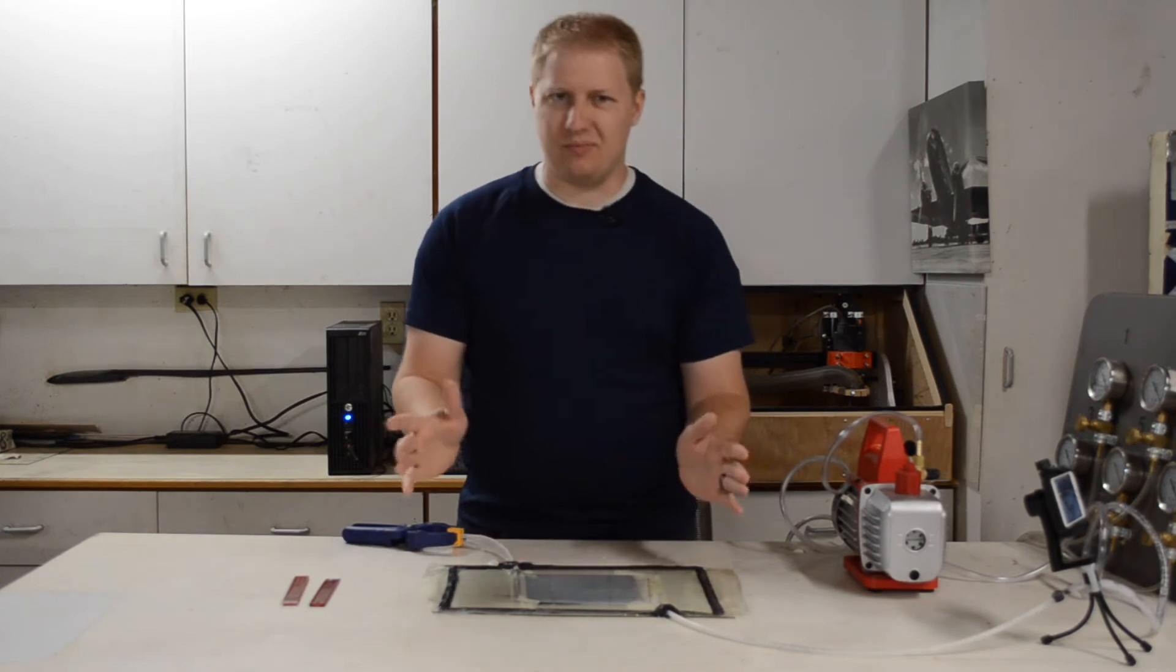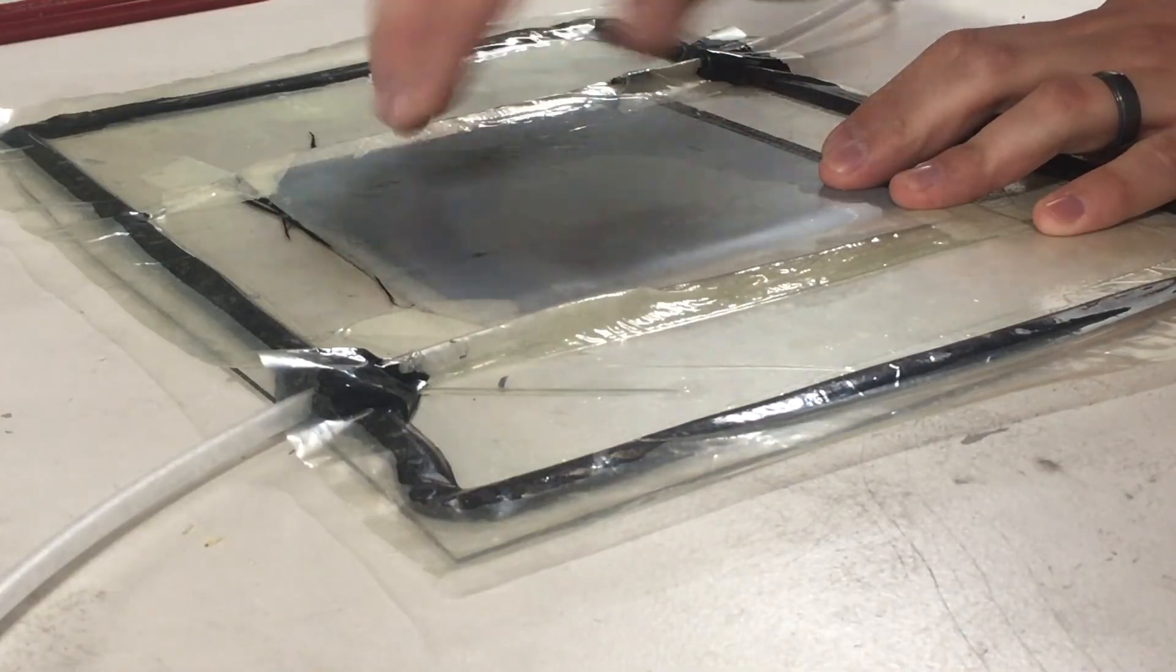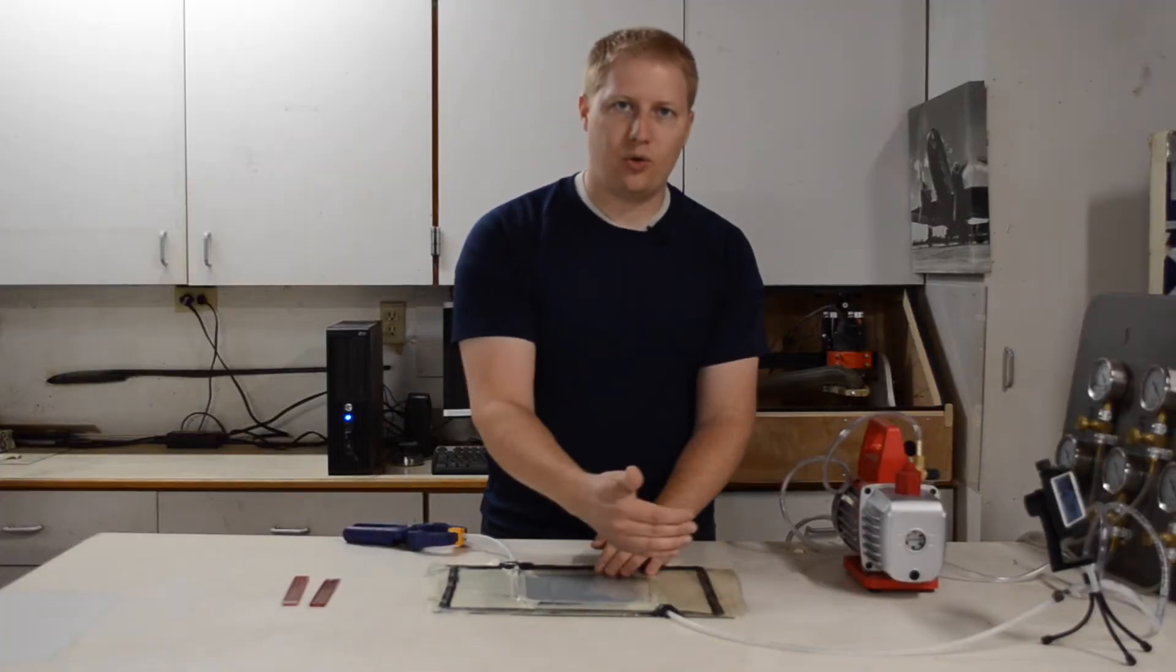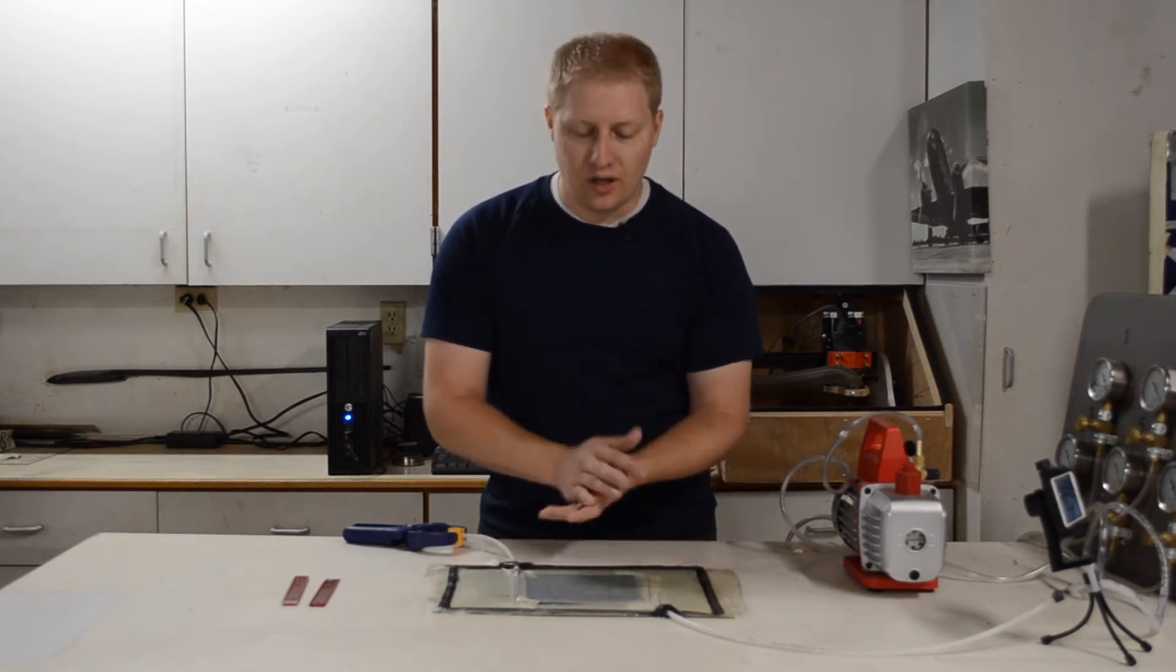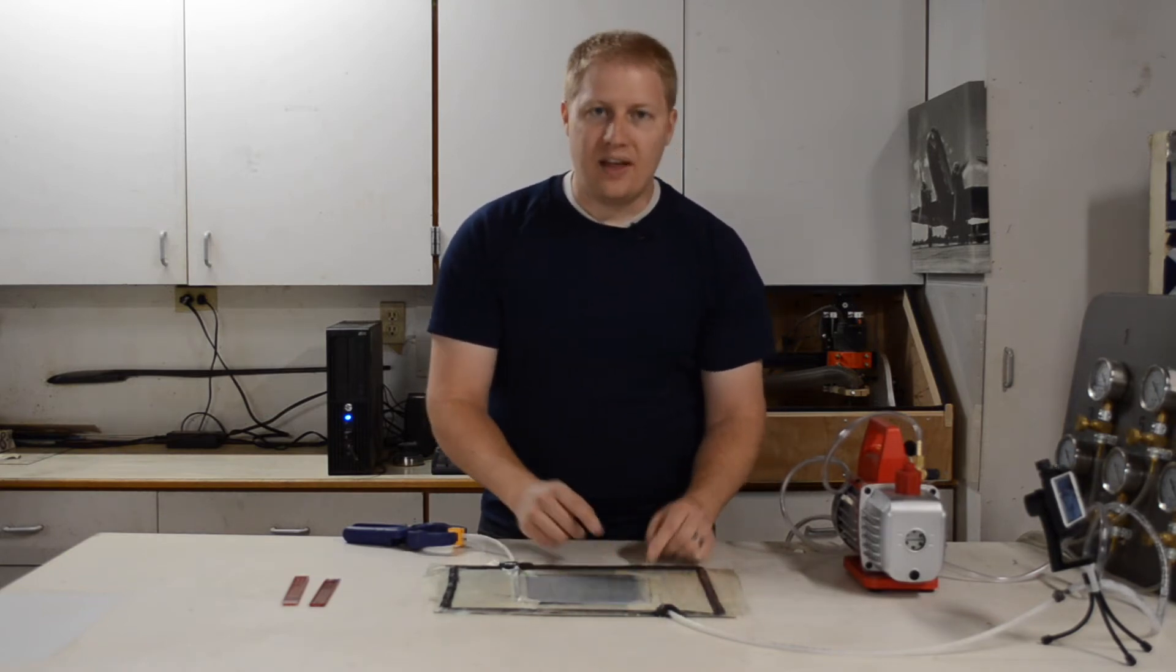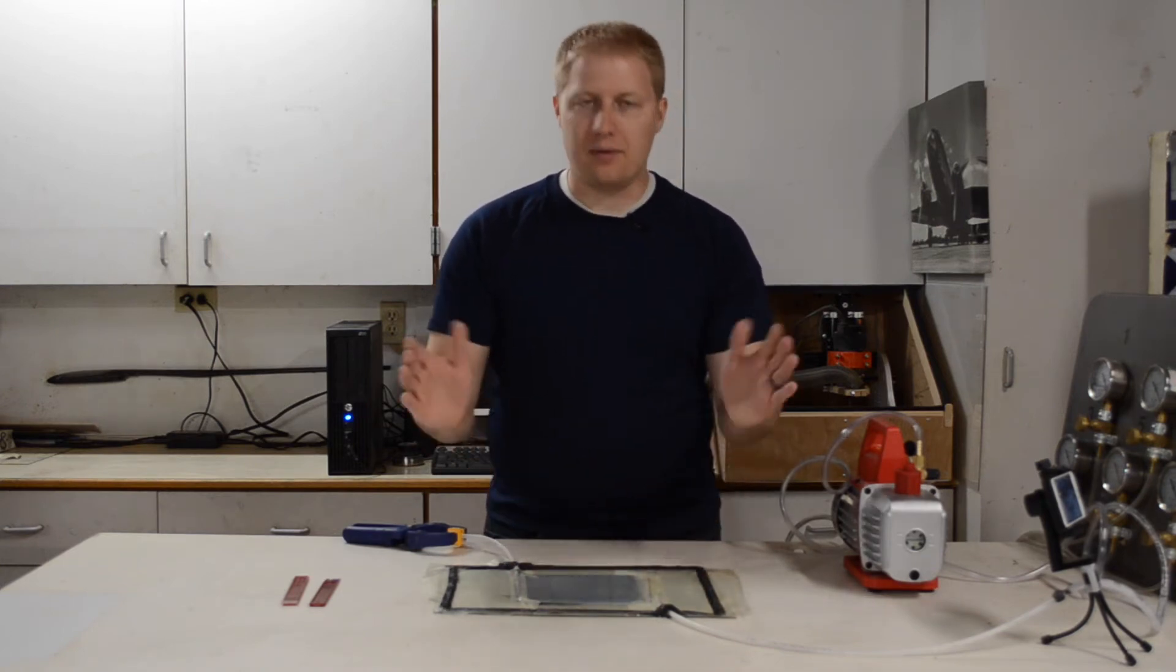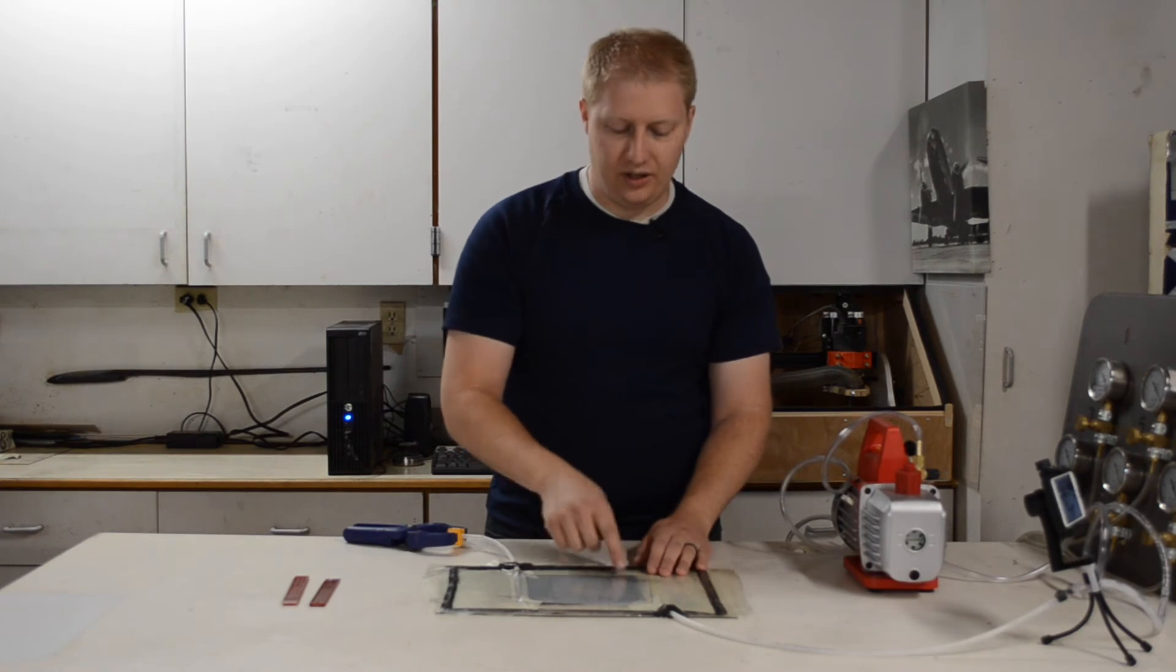The other thing, a mistake that I made, or something that I learned. The mylar, if you looked at it, the mylar actually right here along this edge hangs over the carbon. On this edge, the carbon sticks out. On this edge, the mylar hangs over the carbon. And what that meant was that there was a channel right along there that allowed resin to flow through it. And so it acted almost like this coil here, except it was on this side of the part as well. That wasn't intentional. And so the resin started along here, and then it worked its way from here inward, and this was the last corner that got infused. That was not intentional. And the only bad part about that is that the resin reached my vacuum tube first, before it infused the entire part. A minor thing, because it ended up working out just fine anyway, but it started sucking some resin into there before we actually had finished infusing the part. Again, it worked out just fine anyway.